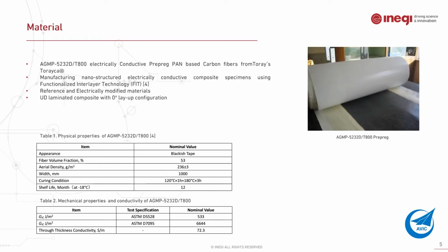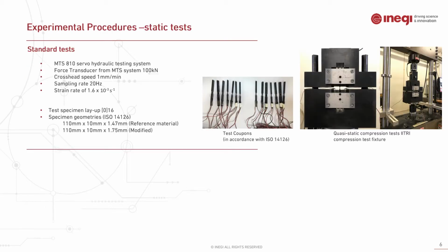So the base material of this study is epoxy resin-based pre-preg reinforced with carbon fibers, which we call the reference material. On the other hand, we have the modified material, which is basically the same material with an interleaved layer of silver nanoparticles. The configuration is unidirectional, and these experiments will cover only compressive loading at different strain rates. So this study will cover the compressive behavior of this material under dynamic and static loading conditions.